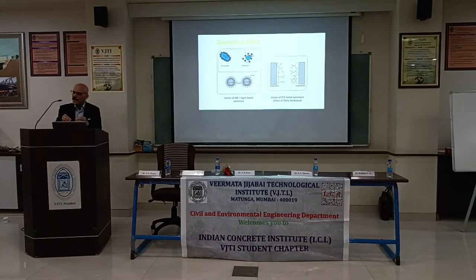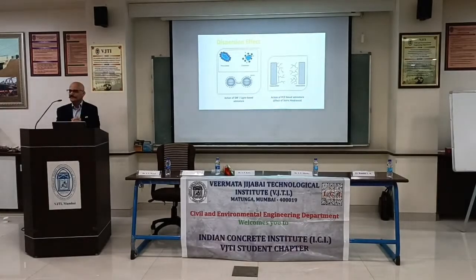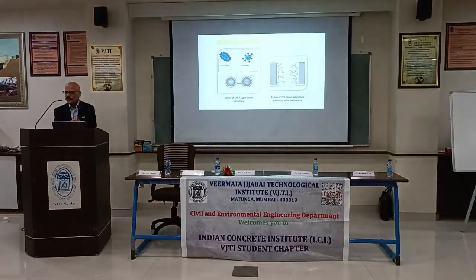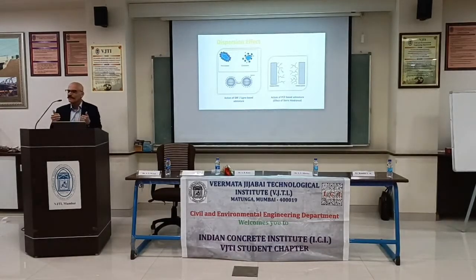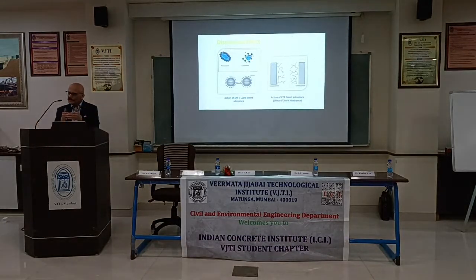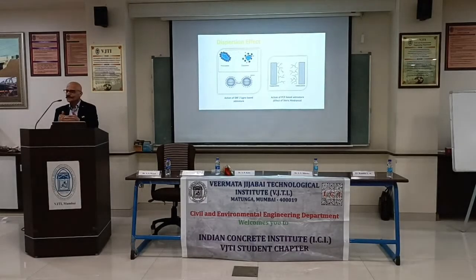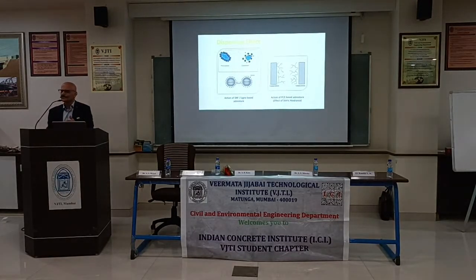So when you add superplasticizer in concrete, suddenly there is a flow, because water is already there, but it is trapped. So there is suddenly flow, and your mix becomes mobile. So with less water, you can have a mobile mix. So you can reduce your water cement ratio. And when you reduce your water cement ratio, void content goes down, density goes up, and your strength goes up.